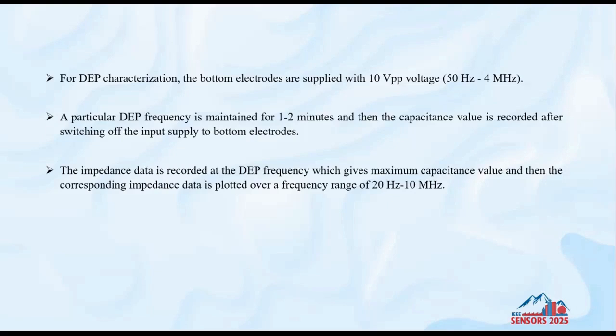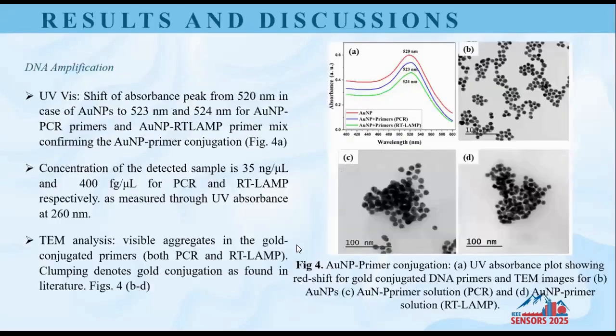actually gives us the double layer capacitance, is measured through the impedance analyzer. And then the impedance data is recorded at the DEP frequency, which gives the maximum capacitance value. Then the corresponding impedance data is plotted and evaluated using an AC voltage excitation of 500 millivolt RMS over a frequency range of 20 Hz to 10 megahertz. The DEP frequency is actually maintained for 1 to 2 minutes, and then the capacitance value is recorded after switching off the input supply to the bottom electrodes. So this is done so that the signals don't interfere between the 2 electrode layers.